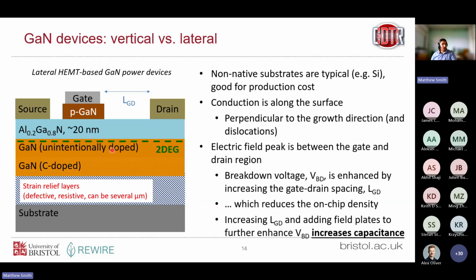And in terms of how much breakdown voltage we can achieve, remember, breakdown voltage is a really important metric here. That scales with the distance between the gate and the drain. So if we increase this gate-drain distance, then we increase the breakdown voltage. Again, that comes at the cost of on-state resistance. But crucially, when we increase this distance, we reduce the number of devices we can fit on the chip. We're reducing our power per unit area because this scales with the area of the device.